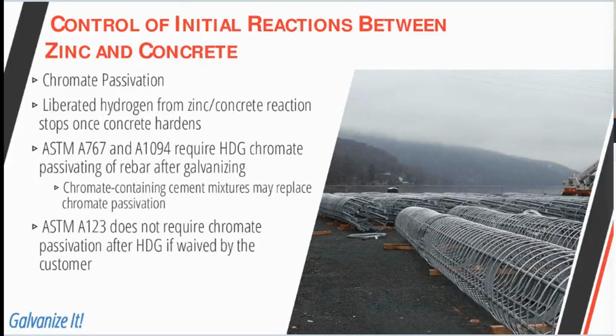However, if you are using rebar that has been out in the field for several weeks to several months, the passivation from the chromate quenching does not last longer than about that time period. So you would need to check to make sure that the presence of the chromates is still there. Otherwise, you could add chromates to the concrete mixture. International supplies or concrete supply to states with higher environmental considerations for those types of materials, they would also need to be checked to make sure that sufficient chromates are in the overall solution in order to limit these reactions.